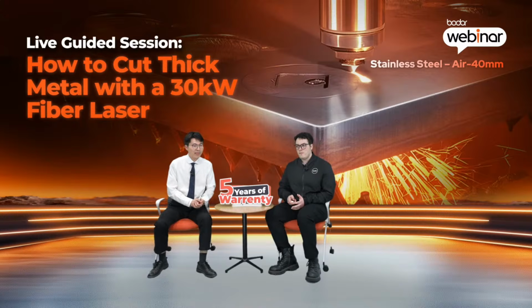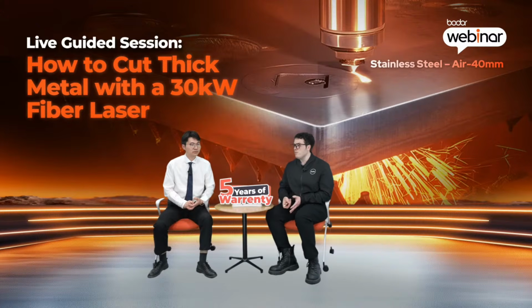Yes, for 40 millimeter stainless steel with air, the setup is the focus is set to minus 17.3 millimeters. The cutting speed ranges from 0.8 to 1.8 meters per minute. And we are using a single layer 5 nozzle.